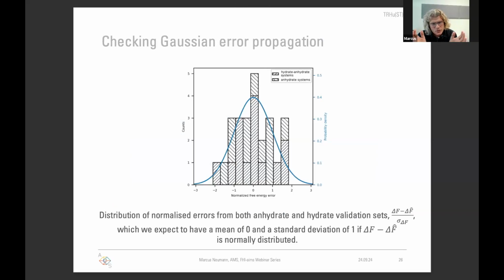I've said we assume Gaussian error propagation, and of course that somehow has to be justified. And so what has happened here is that we took all the experimental free energy differences. We calculated our computed free energy differences. We can subtract the two. So this is actually then a difference of differences of free energies. For that calculation, we can predict an error based on our error estimation model. We can divide the observed error through by the expected error. And if this has Gaussian behavior, then we expect to see a distribution which is a Gauss distribution around 0 with a width of 1.